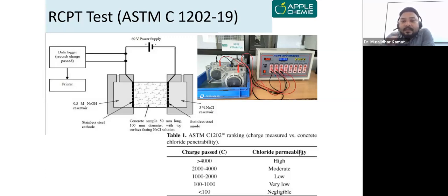And then you are going to check with this apparatus, where we are passing the charges, as you can see in the images. Then you will check the readings. Let's say you make M30 grade of concrete with and without crystalline admixture. Without it, M30 gives 2000 to 4000 coulombs. When you add the crystalline admixture, it will come from moderate to low or very low region, meaning 1000 to 2000 coulombs, or even 100 to 1000 coulombs.